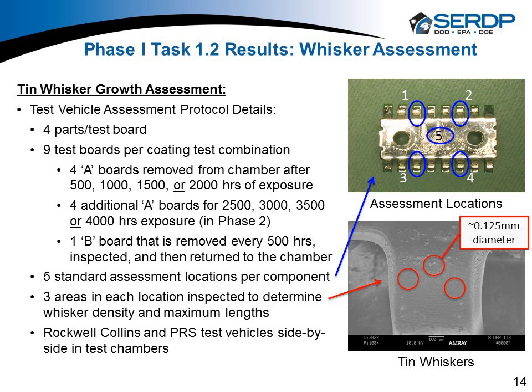And from our industry work, of course, where the lead is bent, when it goes lead forming, down here you can see that's the high stress area, and that's where we saw most of the whiskers initiate and start to grow. We also did a second set of boards based on some discussions with Dr. Steph Meshner from BAE and some of the work they're doing in their SERDP projects.